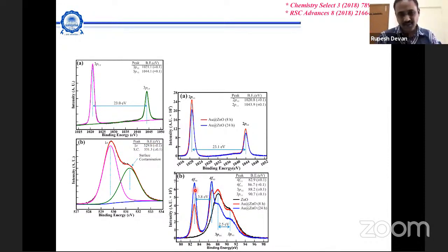And what we are observing is that as soon as you move to more reaction time, the number of gold particles is increasing. That's what we have observed even in XPS. As soon as you increase the reaction time to 8 hours, your gold concentration increases. For 24 hours, it has become more again.